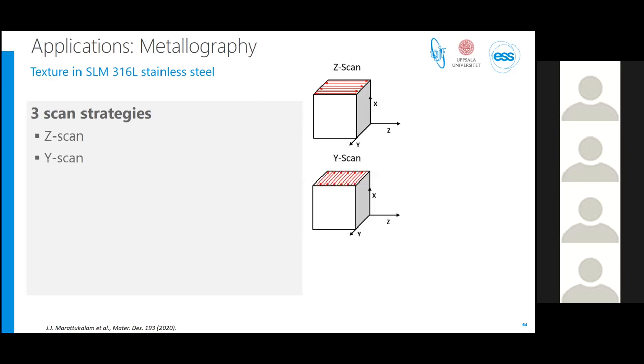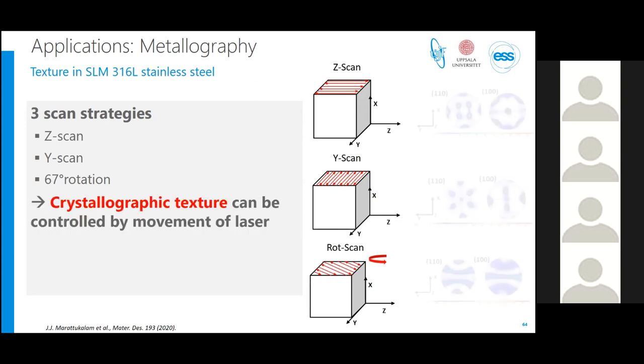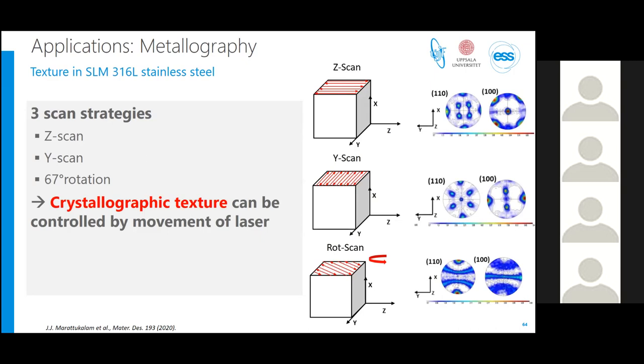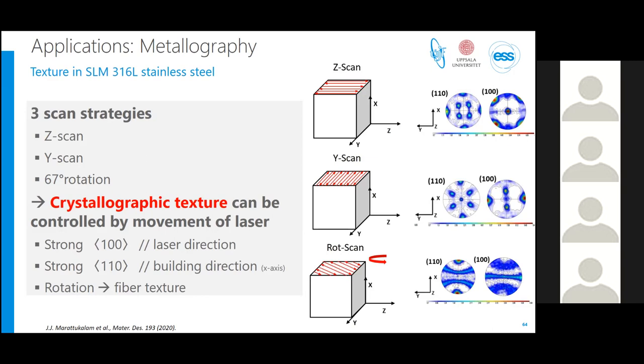In this example, we again looked at selective laser melted stainless steel samples, and my colleagues from ESS and Uppsala University previously used neutron diffraction to look at textures of these SLM samples. They made samples with three different scan strategies, meaning the laser moved along the Z direction, along the Y direction, and then it was rotated during the build process. What they have shown is that the texture can be controlled by the laser movement, how the laser is scanned. For instance, we have a strong 100 texture parallel to the laser direction, and a strong 110 texture parallel to the building direction. And the rotation scan then resulted in a typical fiber texture.